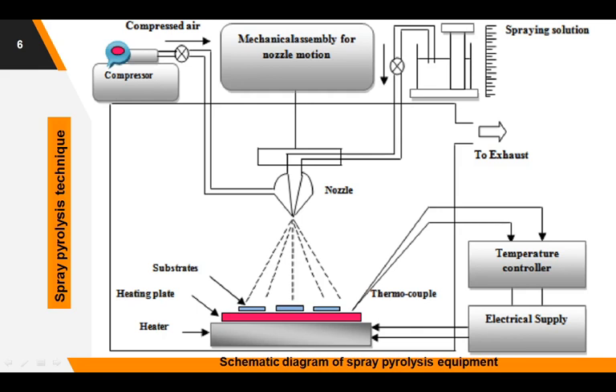The spray nozzle rotates to cover the entire film area. A rotor is required for the movement of the spray nozzle — similar to a car wiper moving from left to right — and a simple electric car wiper motor with specification 12 volts, 2 amperes can be used to rotate the spray nozzle, along with a speed controller. The liquid level monitor measures the spray rate: at a fixed pressure, the spray rate depends on the height of the solution, measured relative to the tip of the nozzle.